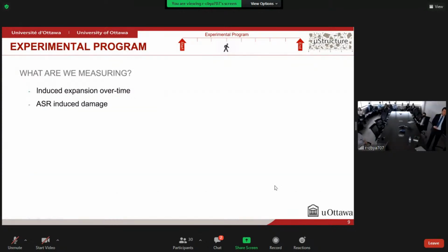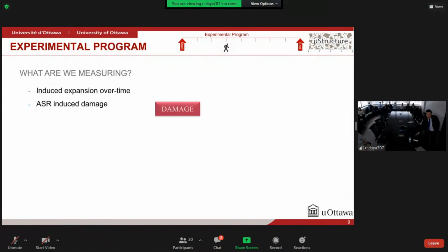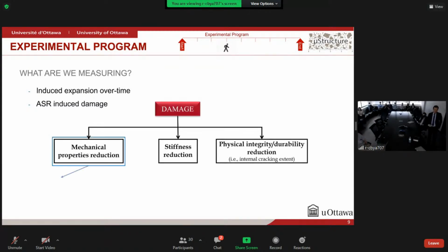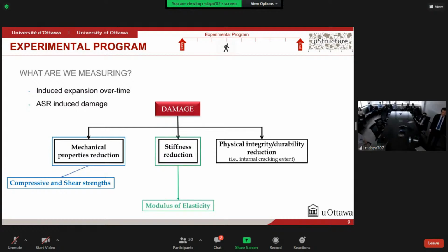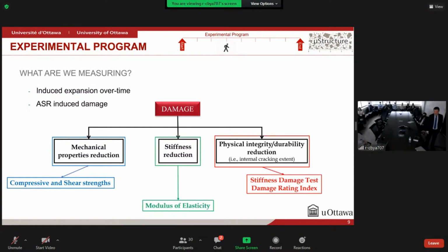So what were we measuring here? First, we are going to be measuring the induced expansion over time of the concrete specimens, but also the induced damage due to ASR. And here, damage is defined as the mechanical properties reduction, which we'll be measuring through compressive and shear strength. Also, the stiffness reduction, which is assessed by the modulus of elasticity, and the physical integrity and durability reductions, with the internal cracking extent of the concrete through the techniques of stiffness damage test and damage rating index, which I will be explaining next.